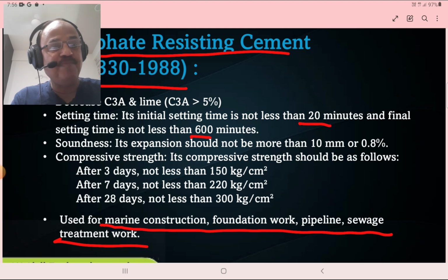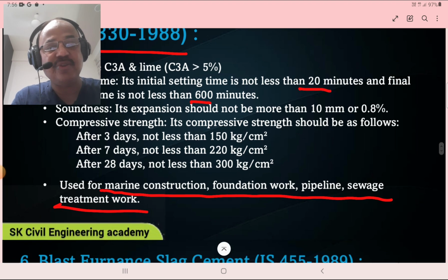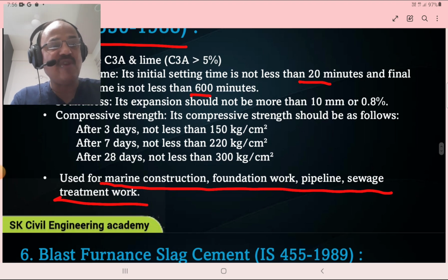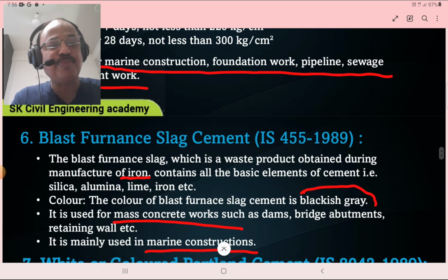Then compressive strength, its compressive strength should be as follows. After 3 days, 150 kg per centimeter square or 15 Newton per mm square. After 7 days, it is 220 kg per centimeter square or 22 Newton per mm square. And after 28 days, it is 30 Newton per mm square or 300 kg per centimeter square. Used for marine construction, foundation work, pipeline, sewage treatment plants. Where there is water and where there is a possibility of contamination of water, in such cases, sulfate resisting cement is used.